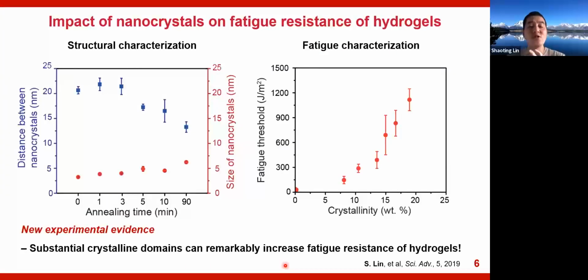To answer the first question, I performed a systematic fatigue study on semi-crystalline hydrogels. I first characterized the average distance between neighboring crystalline domains and the average size of the nanocrystals in a series of samples with controlled growth of nanocrystal domains. Our data shows that substantial crystal domains can remarkably increase the fatigue resistance of hydrogels. This is the first experimental evidence suggesting the important role of nanocrystals on fatigue properties of synthetic hydrogels.